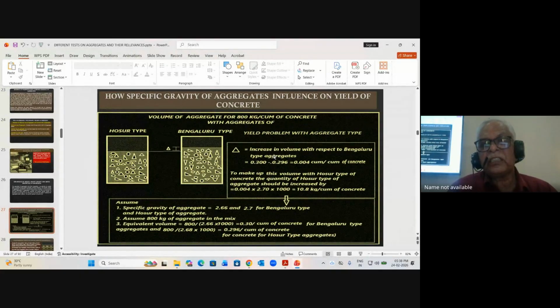Using this absolute volume method, a typical example I consider is 800 kg of aggregate. Using Hosur type aggregate, the volume comes out to about 0.296.